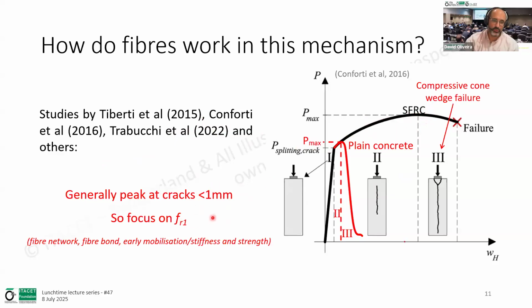So we have to put focus, and that's one of the messages of these studies, that we have to put focus on the smaller crack with resistance or the flexural. In this particular case, the way we typically test is by testing the residual flexural strength at lower or serviceability limit states that we generally refer to, but it's more focusing on smaller crack widths in the order of 0.5 for the crack mouth opening.